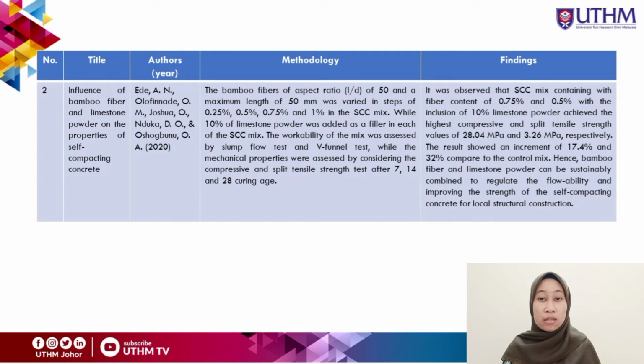Then the finding is, it was observed that SCC mix containing the fiber content of 0.75% and 0.5% with the inclusion of 10% limestone powder achieved the highest compressive and split tensile strength values of 28.04 MPa and 3.26 MPa respectively. The results show an increment of 17.4% and 32% compared to the control mix. Hence, the bamboo fiber and limestone powder can be sustainably combined to regulate the flowability and improve the strength of the self-compacting concrete for local structural construction.